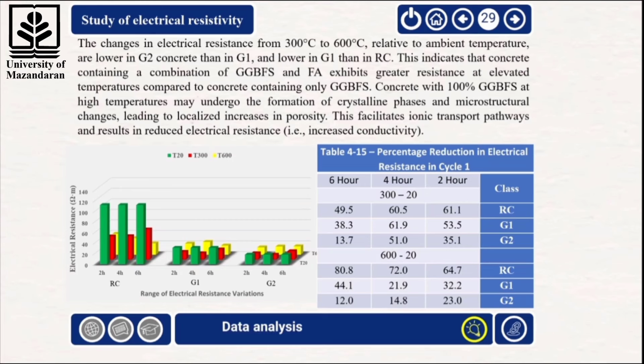In contrast, concrete containing 100% GGBFS tends to form crystalline phases and undergo microstructural changes at high temperatures, leading to localized porosity and facilitating ionic transport pathways. As a result, its electrical resistivity decreases while conductivity increases.